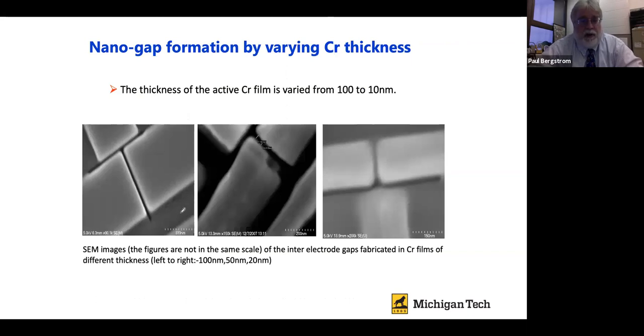Now, we did continue working on etching and we were able to get this down considerably smaller, but we still were limited to about 17 nanometers for our minimum features. So we were able to produce structures that had gaps on the order of 17 nanometers that were useful for our devices. And I'll show you some of that work, I guess, here.